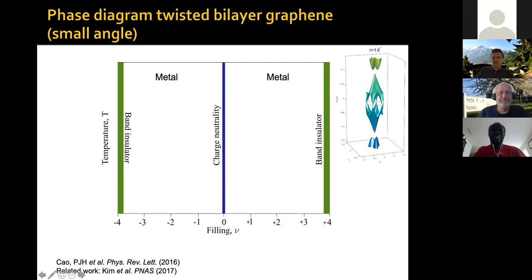These are now Moiré bands, and this is the closest to charge neutrality set of Moiré bands. And then you have these other, sometimes we call them remote bands. There is a separation of a band gap here. So you see, to fill from charge neutrality all the way up to the band gap, we need 4 electrons per Moiré unit cell. So when you reach that point, you reach a band gap, so you have a band insulator once you fill 4 electrons per Moiré unit cell.